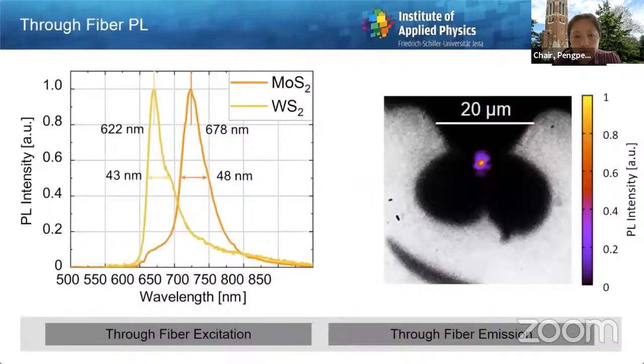So as a first thing, we were looking into photoluminescence. So we look at the exit port of the fiber, we send it through a few long pass filters, and you get this nice spot of light, which is emerging from the core of the optical fiber. And you can then measure a spectrum from this, and depending on which material of the fiber, you really see these nice photoluminescence peaks, which just look like the photoluminescence peaks from your pristine material, which is on a planar substrate.